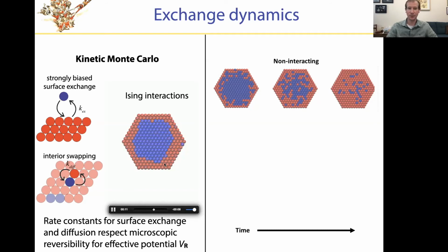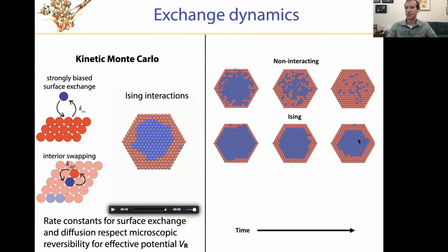What's happened is that it's formed neat interfaces between domains that are red and blue, much like a system at phase coexistence, that are then very, very slow to advance because it involves deforming that interface between them. So this is a case that is kinetically not at all conducive to exchange beyond just the shell of this material. It hardly penetrates much into the core. And indeed, we've seen experimental results that look just like that.